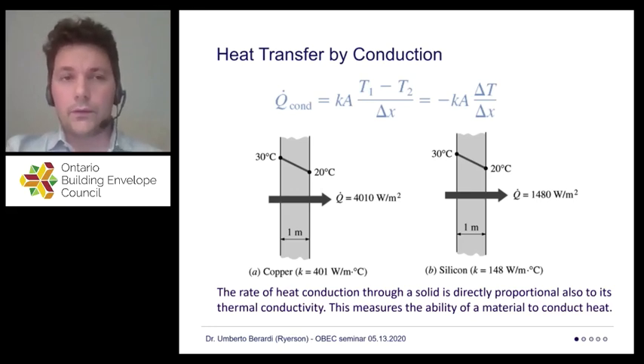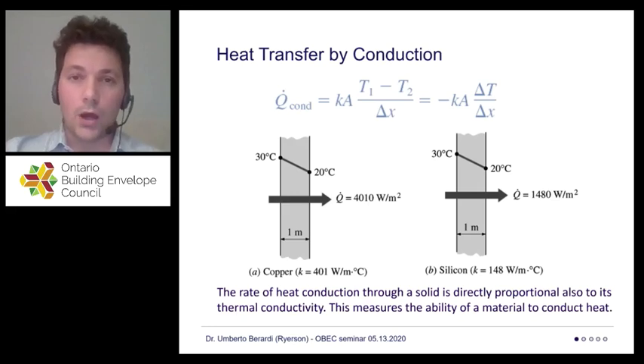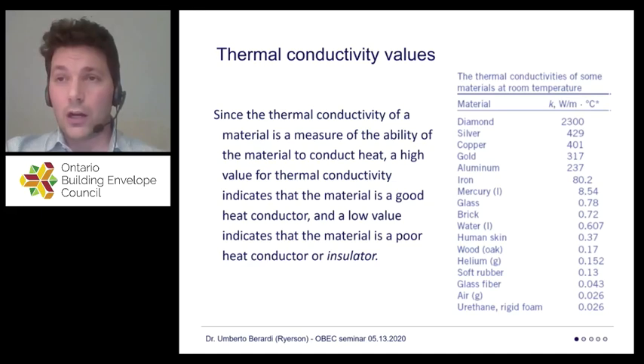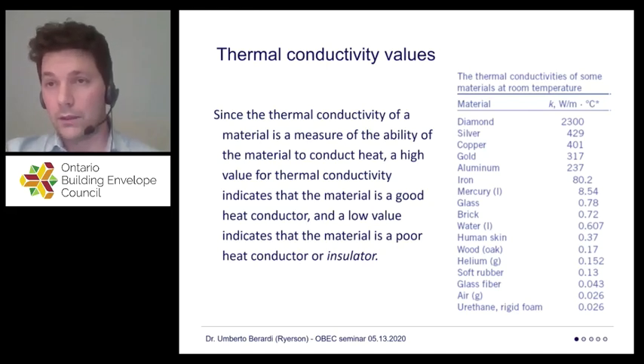So just to memorize and get a sense of these different ideas, assuming I have an enclosure that has 30 degrees on one side and 20 degrees on the other side. If this enclosure is full copper, which is clearly not a building enclosure, then because copper is a poorly insulating material, it's quite conductive as a material, the thermal conductivity, the lambda, is quite high, a few hundreds. And if you start getting silicon, this drops to 100, 150. And then, as you probably may memorize already at this point, we have a lot of materials that have a thermal conductivity in a fraction of 1. Quite a small fraction of 1. So the majority of the products we typically use for insulating our enclosure often have a thermal conductivity ranging from 0.05 to 0.1 watt per meter Kelvin. So it's quite a low number.